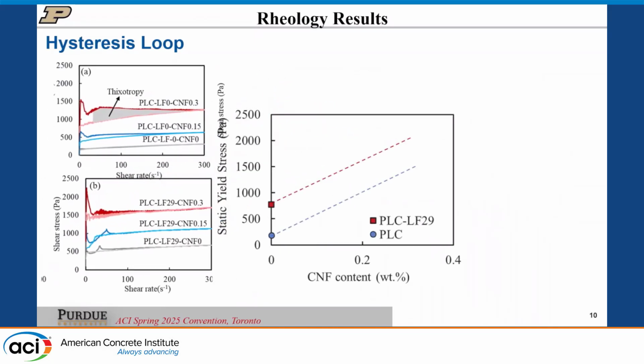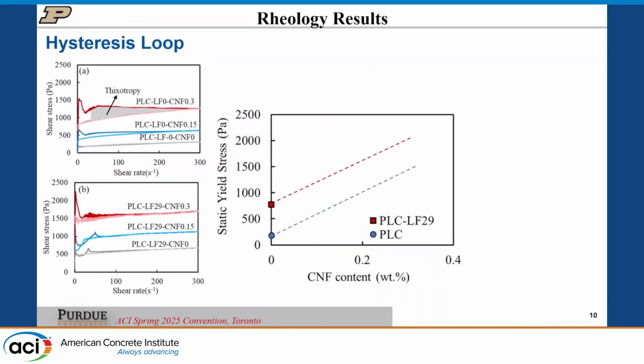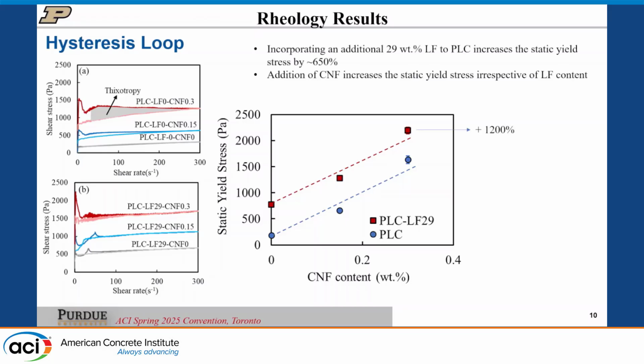The second thing we can take from this graph is looking at the peaks, which give us the static yield stress. Comparing the PLC system to PLC with high limestone filler content, we see a significant increase in static yield stress. But critically, when we add CNF to the system, we have an increase in static yield stress that's more or less independent of limestone filler content. We're able to gain significant static yield stress with very low dosages of CNF, independent of how much cement was in the system, at least for the range we looked at.